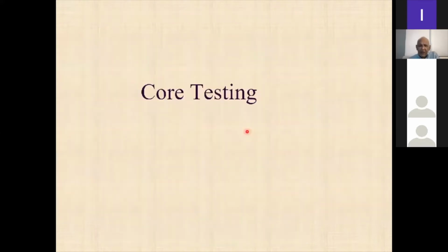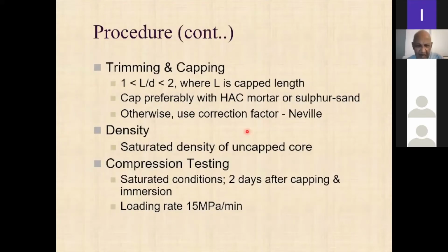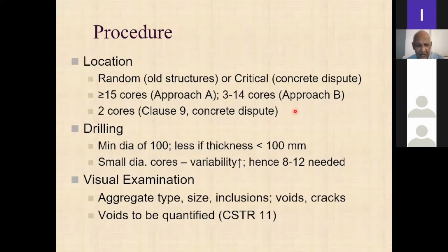Now, if we look at core testing, these are some slides on core testing, right? So these are repeating sometimes what I said earlier. For approach A, you need more than 15 cores. Approach B, 3 to 14 cores. If you have a concrete dispute, at least 2 cores you will need, right? So minimum diameter of 100.